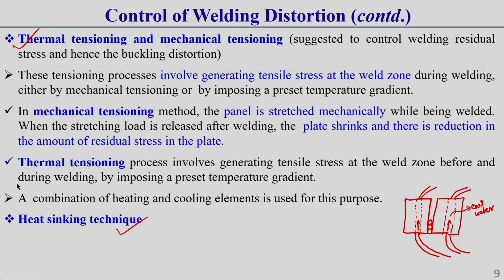Now, here you see thermal tensioning and mechanical tensioning. These two tensioning methods are very popular. Always keep this in mind. In these techniques, we apply some tensile force in the weld zone during and before welding. You should keep this in mind. After welding we release this tensile force, and once we release it, it minimizes the distortion as well as the residual stress.